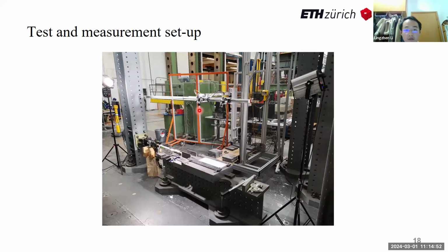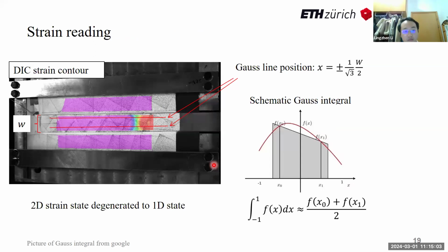And during the test, two DIC cameras were capturing pictures for later processing of the full-field displacement and the full-field strain of my specimens. Here is one typical two-dimensional strain contour. The contour wasn't straight, but curved. This means the strain state and the stress state in the shape memory alloy feature a typical membrane stress state. This brought some difficulty for us to analyze the bond behavior hidden by the shape memory alloy.